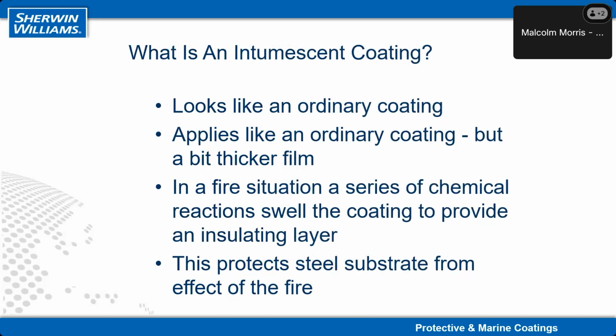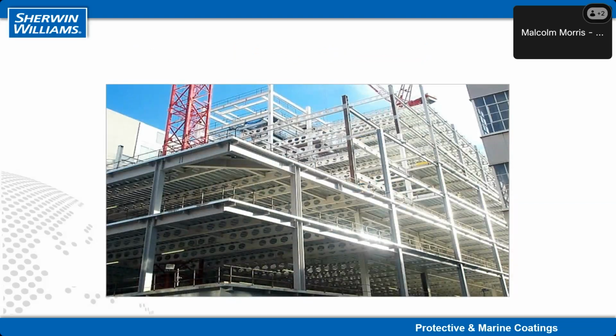It goes on a bit thicker than traditional corrosion protection coatings, but in a fire situation, the pigments in the coating provide a series of chemical reactions which swell up and form a carbon char, which forms effectively an insulating blanket around the steel structure. And this insulates the steel from the effect of the fire and delays the rate at which the steel heats up in the fire situation. That is typical structural steel, which I don't need to introduce any of you guys to. I'm sure you're well familiar with that.